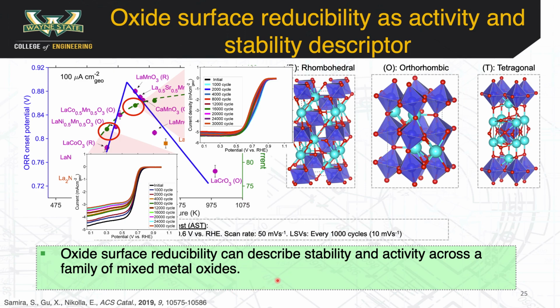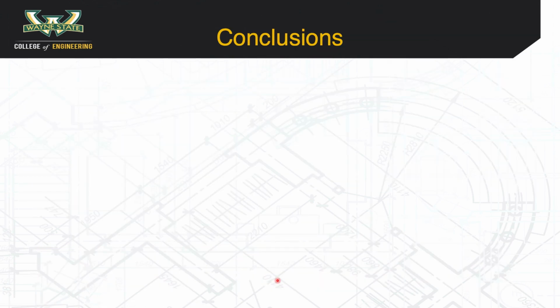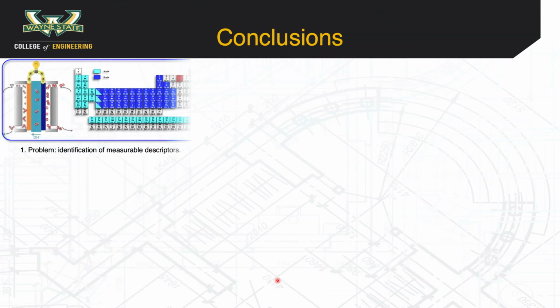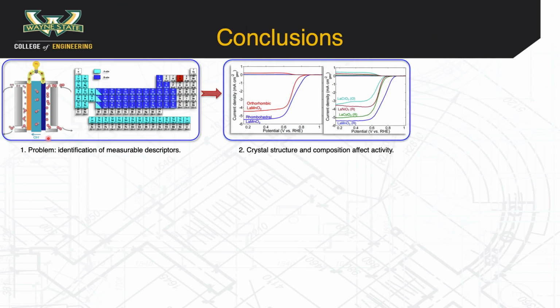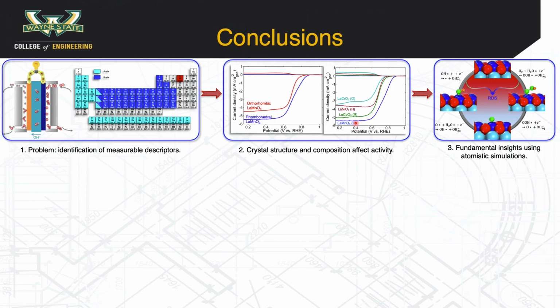mixed metal oxides. To conclude, I'd like to remind you that I initially started off with defining the problem statement as identification of measurable oxide properties to describe the electrocatalytic performance of these mixed metal oxides, using the electrochemical oxygen reduction reaction as a probe reaction. It is observed that both the crystal structure and the composition of the oxide affect the electrocatalytic activity. These experimental observations were then benchmarked using fundamental insights from atomistic simulations.